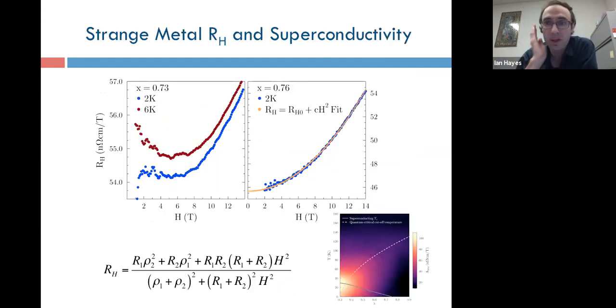If you continue all the way to the overdoped, the very edge of the superconducting dome, at like 73% phosphorus substitution, this is a sample with about a 1 Kelvin TC, it's right on the edge. You see a very small, 2% or so decrease in RH at a few Kelvin. And then if you go to the next sample over, you don't see any decrease at all at 2 Kelvin. What you see is a pure H squared fit, which seems well described by simple multiband. So you can see directly by eye that whatever this decreasing RH is at low temperatures, it vanishes at the same time as superconductivity.